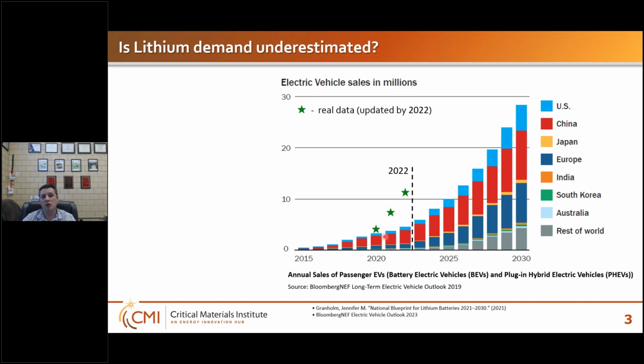The US also has 20 sites in lithium-rich hard rock minerals, with the Kings Mountain in the Carolina Spodumene Belt being the largest deposit, with an estimate of around 5 million metric tons of lithium, which is comparable to what Australia has. However, despite this fact, and the fact that there is much less lithium in brines compared to, for example, spodumene in hard rock minerals, still brines are the preferable source of lithium extraction, mainly because they use the solar evaporation process, which is cost-effective and economical. To extract lithium from hard rock minerals, the processes that they use are energy demanding and generate a lot of chemical waste.